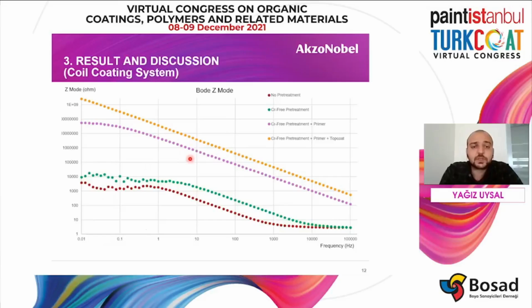We can also analyze the Bode impedance graph of polyester top coats. 20 micron polyester top coat applied on the chromium-free pretreatment and the primer. Actually, we have already analyzed the effect of the pretreatment here in chromium-free pretreatment, and when it's compared to bare metal. When 5 micron primer is applied to chromium-free pretreatment, we have a jump in the impedance value. It gives a better corrosion resistance. And moreover, if we apply 20 micron polyester top coat, impedance value reaches higher than 10 to the 9 ohm.